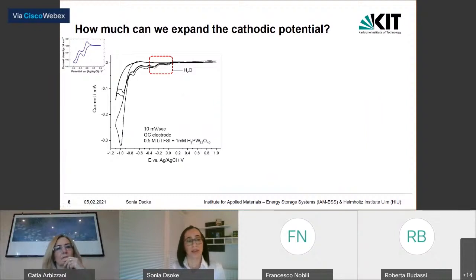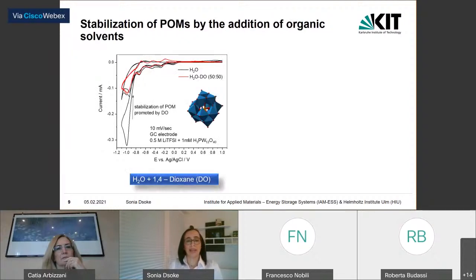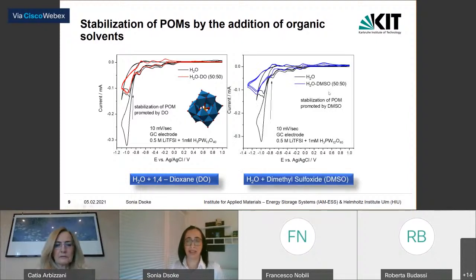One idea to overcome this issue was to mix together with water an organic solvent which is miscible, in this case dioxane, to stabilize the polyoxometalate. And in the mixture, 50-50 in volume of water and dioxane, you can observe also the returning peaks. So the polyoxometalate is becoming reversible. And the same, I also tried by using another solvent, dimethyl sulfoxide. And also in this case, you can observe the returning peaks.